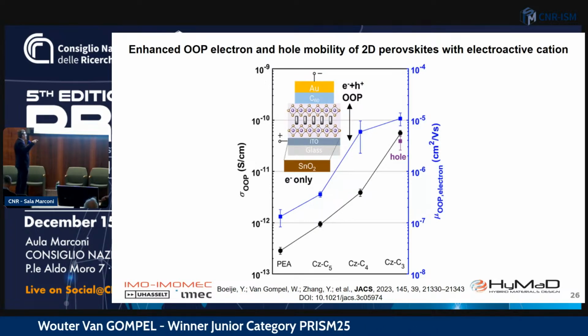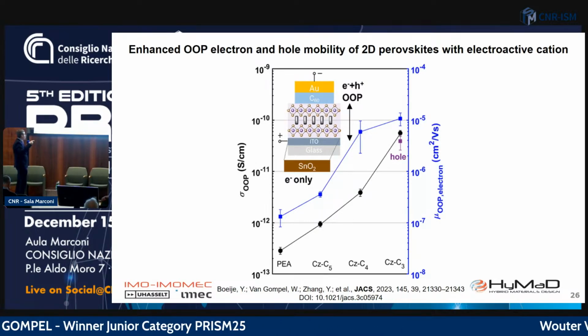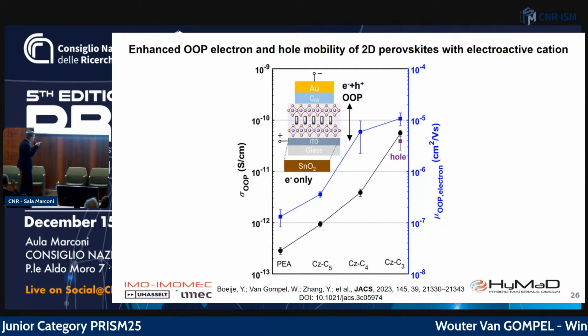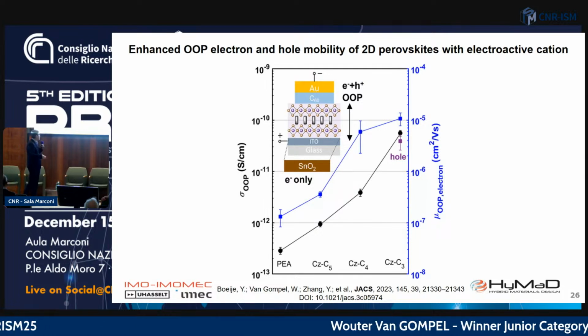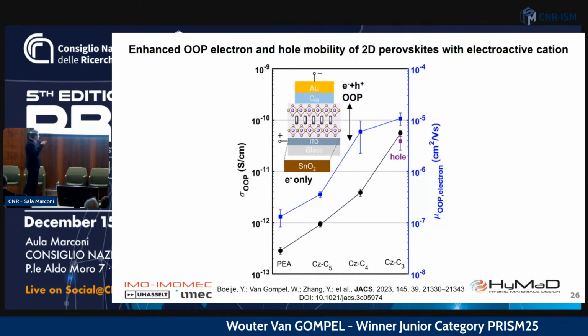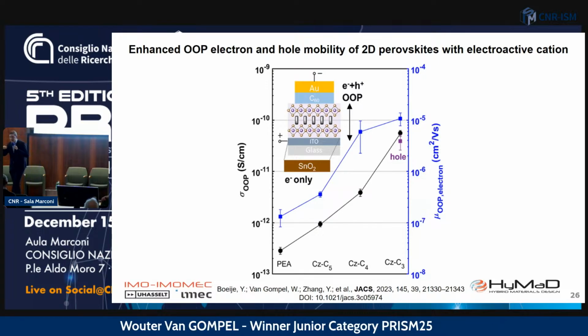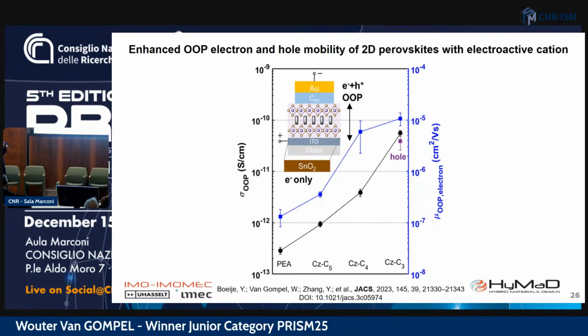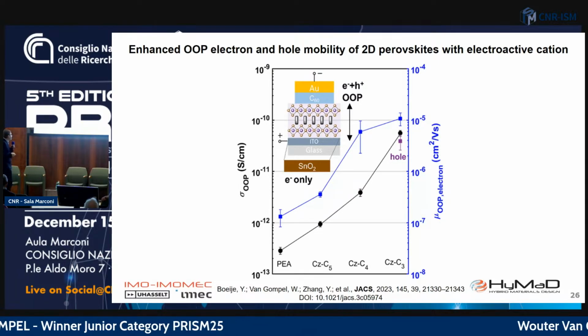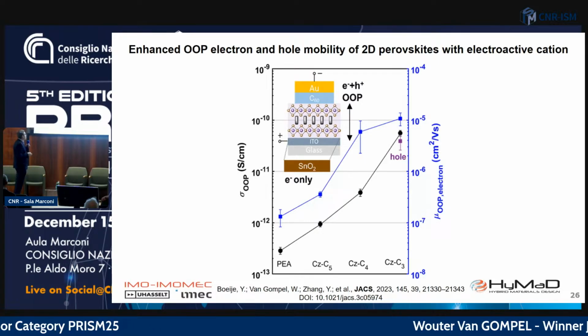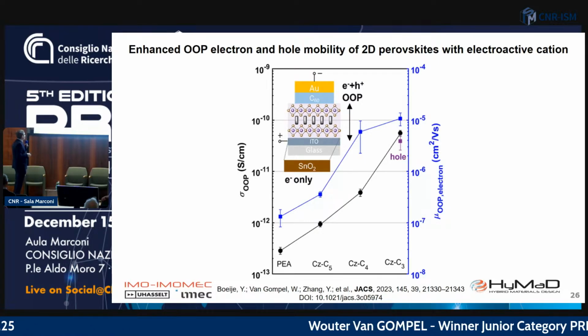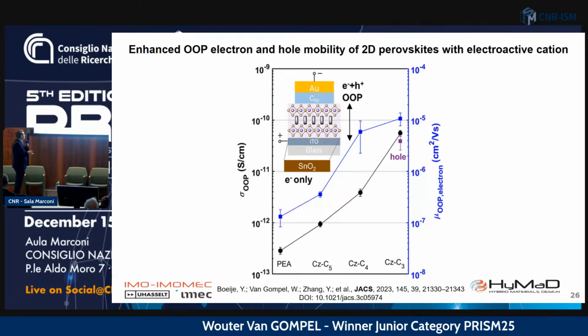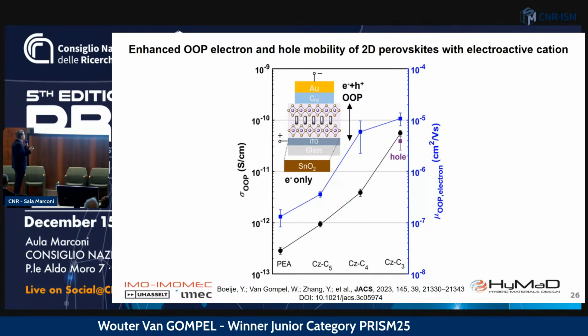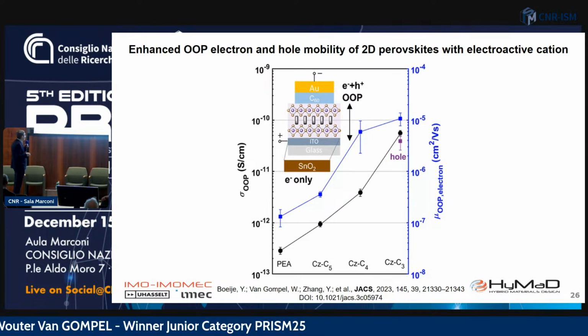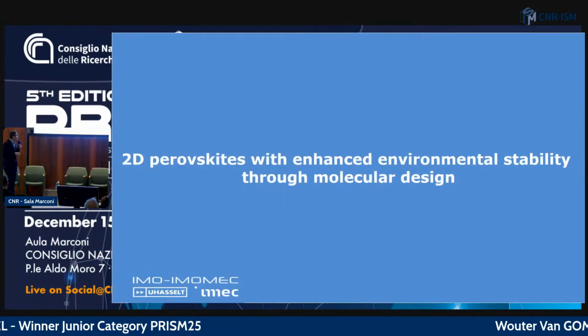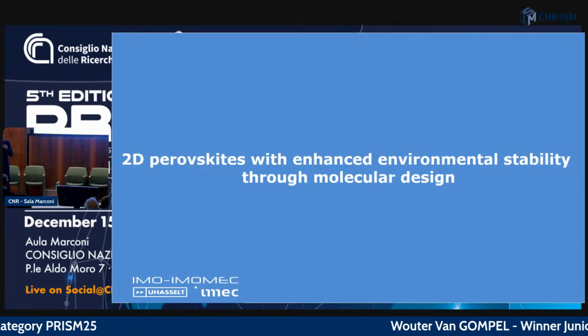But in this case, if you make the organic functional, you get orders of magnitude higher electron and hole mobility in these materials. Okay, they are still quite far from the inorganic, but we are making progress there in designing the right organic molecule to improve the hole and electron transport in these materials. So it's really an example of how the organic can improve or be important in the electronic and optical properties of these materials. So that's one important component of our work.